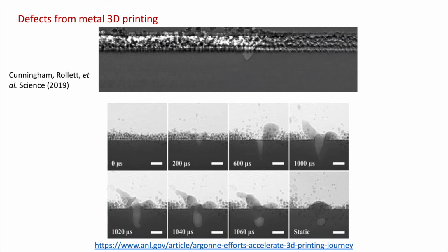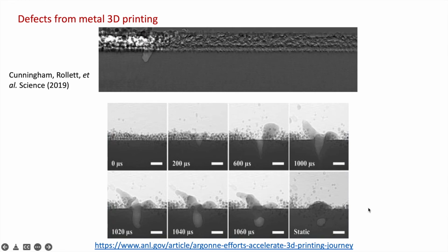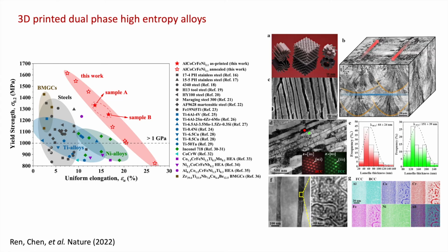In this example, we are lucky as the keyhole did not leave behind at the end of the printing. In some other cases, you may not be as lucky. In the example down here from the Argonne National Lab, as the liquid phase closes off, the keyhole or part of the keyhole actually got trapped inside the material. This will be a pore in the 3D printed metal and will be detrimental to the mechanical properties.